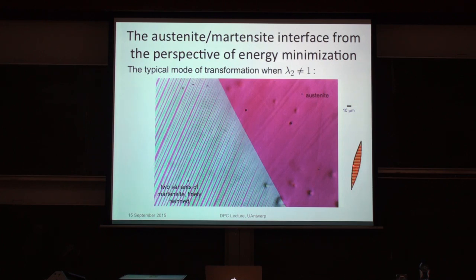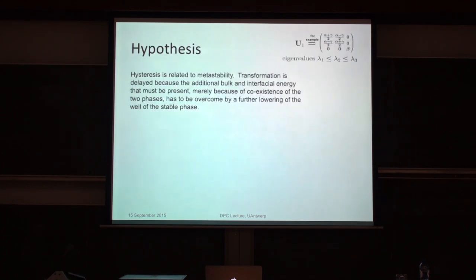by having these yellow and orange bands in here, imagine that we're below the transition temperature. So the free energy of these bands here is less than the free energy of the austenite. So I'm reducing the energy, but then I'm forced to accept the energy on these transition layers. Okay, that's positive energy. And that dominates, in fact, at small scales. So then this is a very thin needle. So in fact, as soon as you have the energy lowering bulk material, you're forced to take energy raising transition layer and interfacial energy. So that creates an energy barrier, and that could be the reason for hysteresis. So I want to explore that.